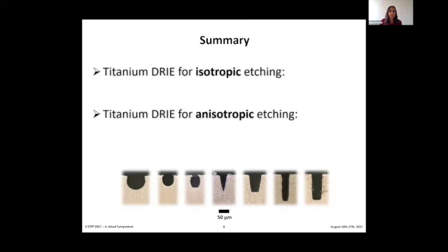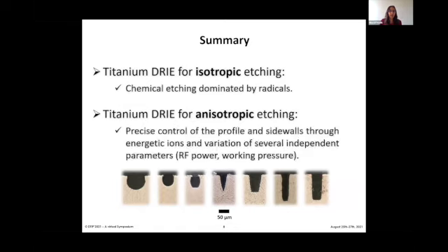Let me briefly summarize the main issues. The experimental results obtained suggest that trenches of varying profiles can be formed by balancing the fluorine radical-assisted isotropic etching, the oxygen passivation film, and the physical bombardment to which argon contributes strongly. An optimized etching process was obtained, and profiles with straighter sidewalls were obtained. However, trench openings were slightly enlarged.